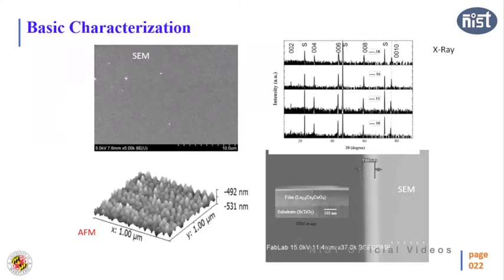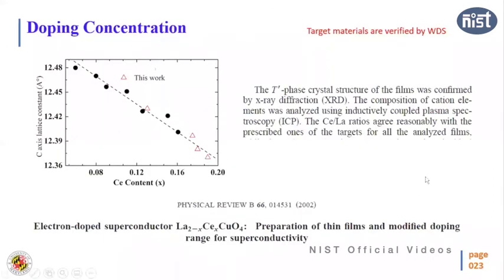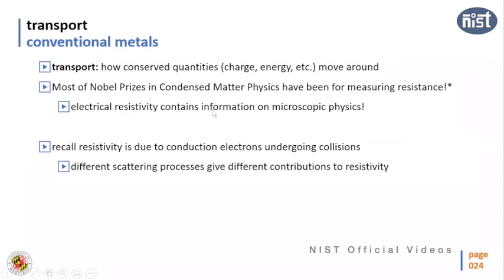Once we are sure that the film is good, epitaxial and quite clean, we check the material composition. Material composition is verified using WDS, and there are other ways to check that the doping concentrations are consistent. For that, we measure the c-axis lattice constant. As a function of cerium doping, you can see how the c-axis lattice constant changes. With a combination of all these methods, we verify whether the stoichiometry of all these films is intact. Once we are done with that, we start the transport measurements. Now, why transport?